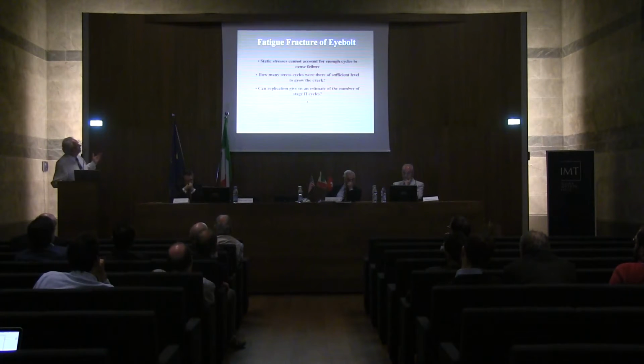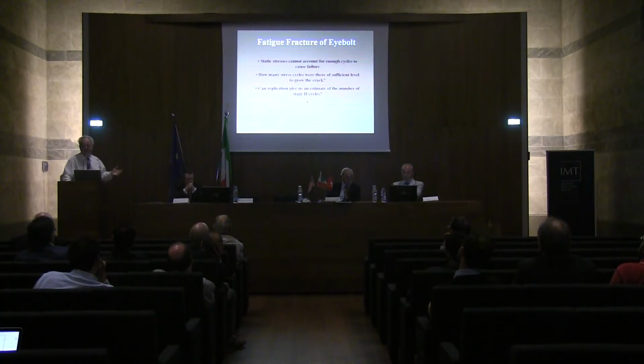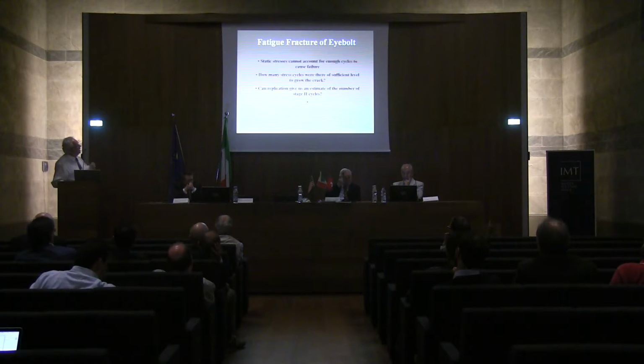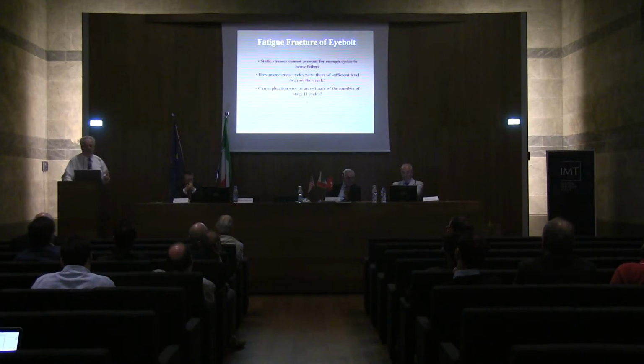Now, the fatigue fracture of the eye bolt was looked at, and static stresses cannot account for enough cycles to cause the failure. No way. That's why Harold's analysis, even with the bending moment considered, was claiming 30 years life, and it only lasted less than a year. So how many stress cycles were there of sufficient level to grow the crack? And can replication give us an estimate of the number of stage 2 cycles?